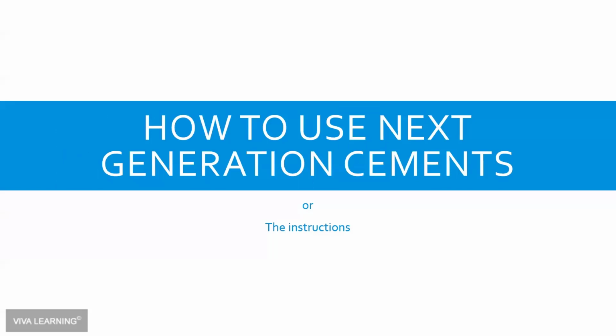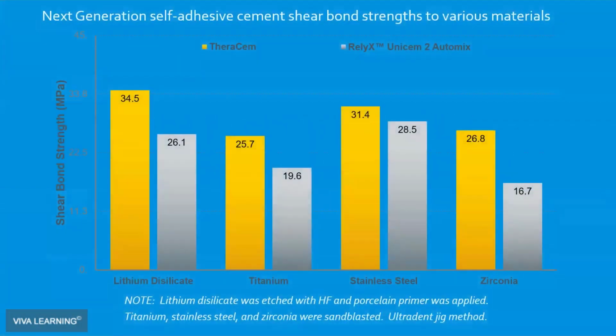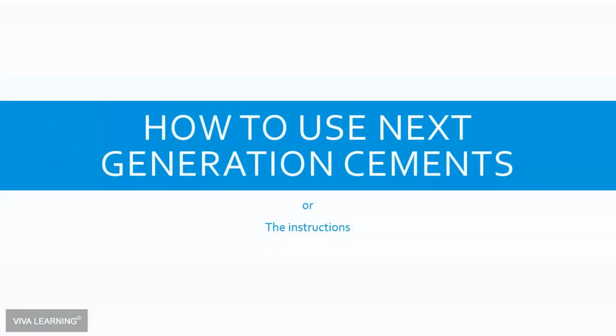We also see that these next generation self-adhesive cement shear bond strengths to other materials, and here we have a comparison between TheraCem and 3M's RelyX Unicem 2. You can also see that there is a difference on the same materials, but with slightly different recipes in terms of what is in the formulation of these and the chemistries of these different cements. But both are excellent, I might add. Both are far and beyond what we were ever getting with glass ionomer or resin-modified glass ionomer.